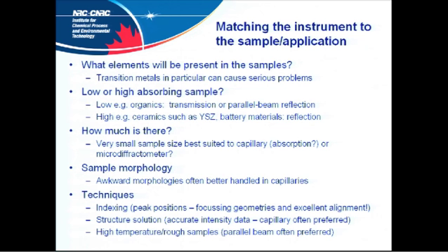Now, sometimes you might find that the requirements of the sample and the requirements of your technique don't quite match, and this starts becoming a bit of a compromise in itself. I think we heard from Peter Stevens yesterday that for indexing, the peak positions are what you really need. For low absorbing samples like organics, for quality data for refining and structure solution, you would ideally use transmission data, but if you don't have transmission data, the intensities are important, so you can get away with thin plate reflection.